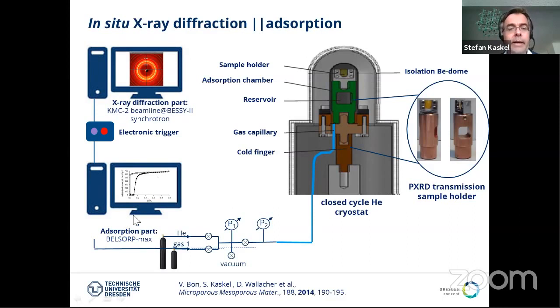So we connect this to a volumetric adsorption instrument, such as the BELSORP-max, for example. And the BELSORP-max gives a trigger to the synchrotron when the sample is equilibrated. And then we can measure an X-ray diffraction pattern in parallel to analyzing the full adsorption isotherm.